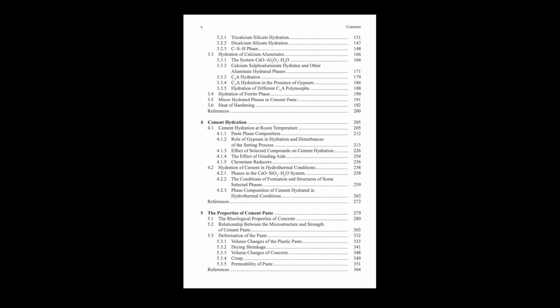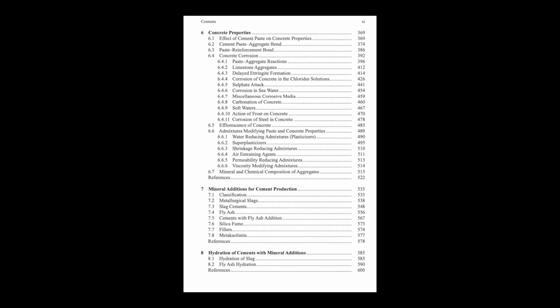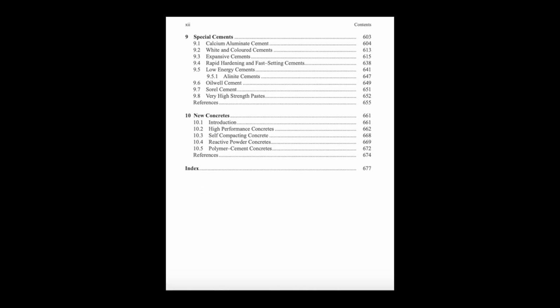What are some key hydrothermal CSH phases? Important ones include different crystalline forms of tobermorite, like 1.1 nanometer or 1.4 nanometer tobermorite, also xonotlite and alpha-dicalcium silicate hydrate. And what forms depends on the conditions. Strongly dependent on temperature, pressure, and the starting calcium to silicon ratio. The source includes a table showing typical phases in hydrothermally treated cement pastes. And subsection 4.2.2 goes into the conditions of formation and structures. What's the key insight there? It discusses the specific T, P, and C/S ratio ranges where these individual hydrothermal phases tend to form and become stable. And it talks about their crystal structures.